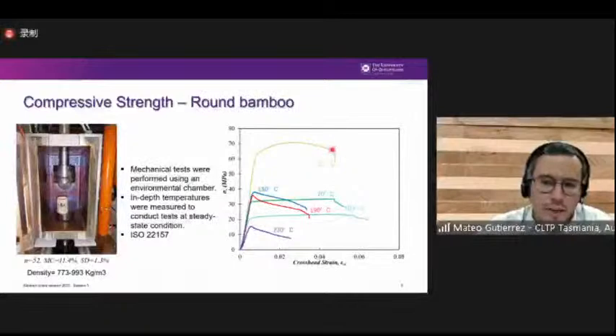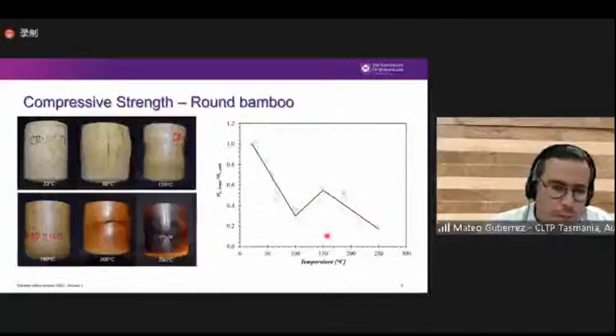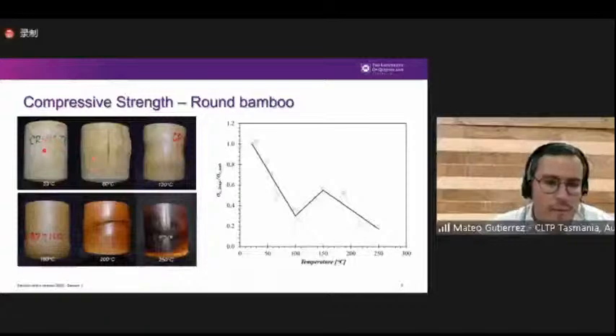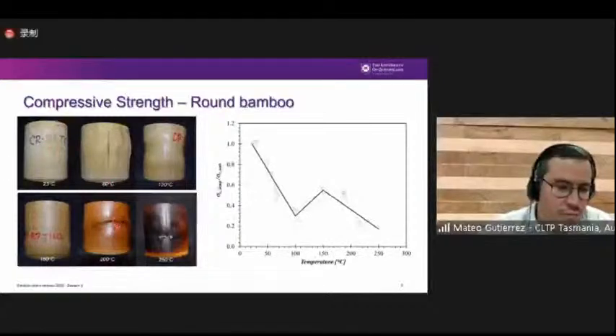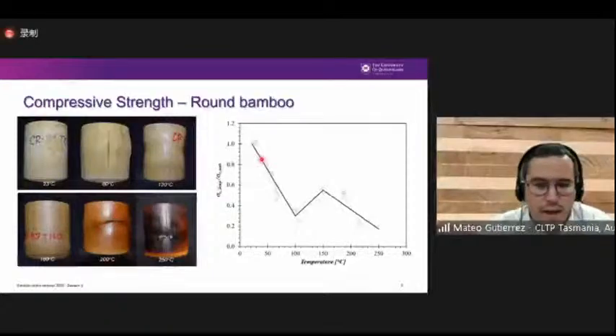So if you look at this curve here, this is normally the stress strain curve for bamboo in compression. And what you can see here is that once you start increasing the temperature, we have lower strength, but slightly higher deformations. So basically we reduce the strength, but we start gaining a little bit of ductility. We observe different failure modes, and we move from a characteristic failure mode to localized failure, like a local buckling in the wall thickness. And then we created these graphs to look at the reduction of the compressive strength of bamboo.